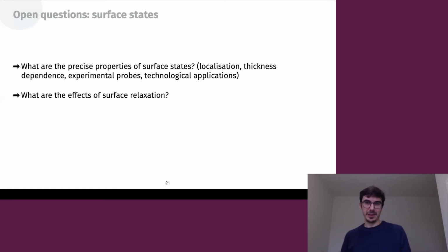And the reason for that is because what we do is we do all these studies using density functional theory, essentially solving the equations of quantum mechanics for specific materials. And the approach we use is to use periodic boundary conditions. Now, when you create a surface, you of course don't have periodicity in the direction perpendicular to the surface, and that means that the calculations become incredibly more computationally expensive.